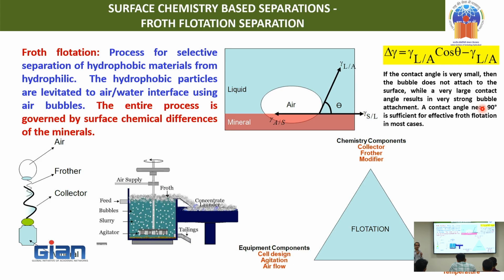Why we are saying hydrophobic and hydrophilic is the attachment in froth flotation. Flotation means you are levitating to the surface using air bubbles. The adsorption of air bubbles on the particles will be facilitated only if the surface is hydrophobic. If it is hydrophilic, the surface tension forces will not allow the air bubble to sit over the mineral surface. So what we can do, there are two ways. Some minerals, for example, sulfides, molybdenite or chalcopyrite: if the cleavage plane is across the sulfur, then the surface is hydrophobic. But in the case of oxide minerals like cassiterite or wolframite or some other mineral, rare earth minerals and all, it is highly hydrophilic.